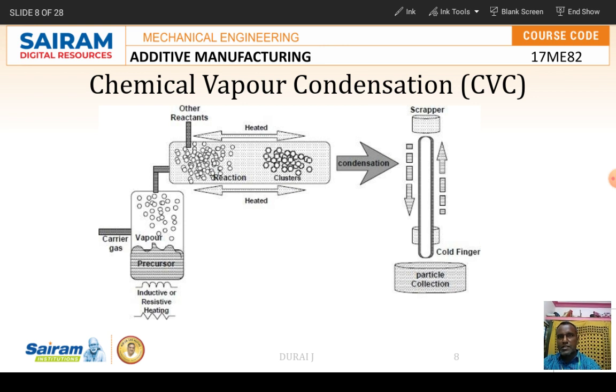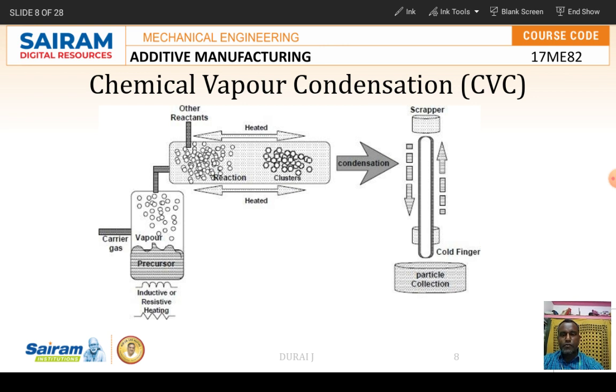The chemical vapor condensation process, using a single precursor reactor, allows the synthesis of a mixture of nanoparticles of two phases or doped nanoparticles by supplying two precursors at the front end of the reactor. Coated nanoparticles — such as zirconium oxide coated with aluminum oxide — can be produced by supplying a second precursor at a second stage of the reactor, utilizing homogeneous nucleation followed by heterogeneous nucleation.